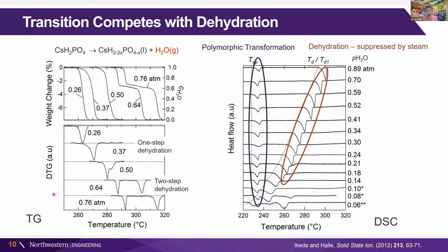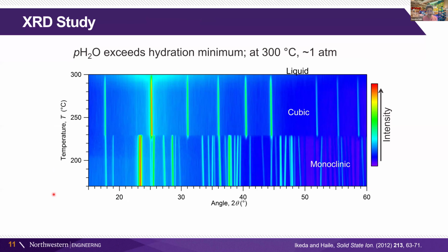Okay. All right, so we also show that if we have enough steam in the system and we do X-ray diffraction measurements as a function of temperature with this high humidification, we can clearly see the cubic phase. We have the simple diffraction pattern of that simple cubic phase, a few lines nicely spaced that match exactly what we expect for the cubic pattern. Whereas at the lower temperatures, we have the monoclinic phase, and we have a nice wide window of stability. So this is clearly not a decomposition reaction.